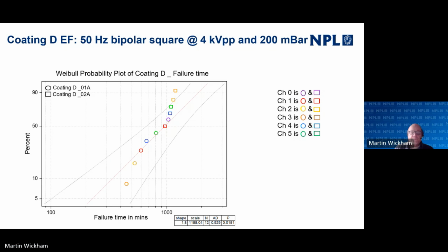The thing about this coating, two different PCBs again, is that there's quite definitely two populations here. I think I haven't highlighted those, sorry, I thought I had. You can see this population here on the second board is giving us a much more acute angle in the line. It's moving outside the 95% confidence levels here, so we're not quite so keen on the result of this line, but you can see that if you wanted to draw two lines, you could probably draw one through the circles for the first sample and one further to the right, with better failure time, for the second sample.